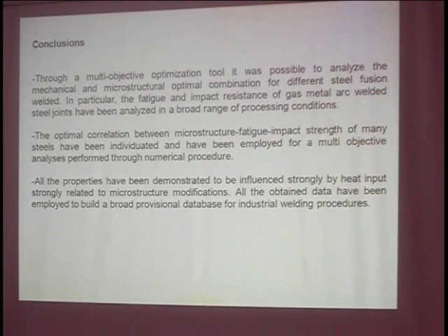In conclusion, this way of working allowed us to build a very big database on many different kinds of fusion weld, gas metal arc fusion weld for steels, and it is an instrument which is open, so it can be improved in its performances on the job. So you introduce new data, and it works much better, and so it's an open database, and it allowed us to have a good predictive tool for the mechanical properties, and we are working to have an optimization in terms of the prediction of the evolution.